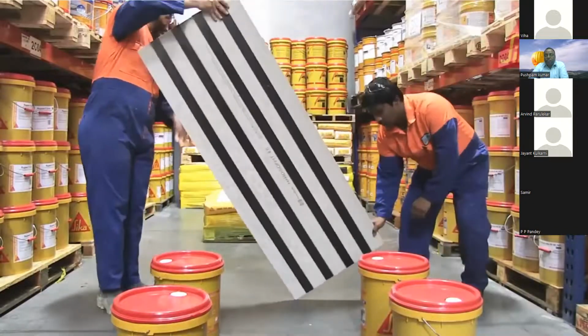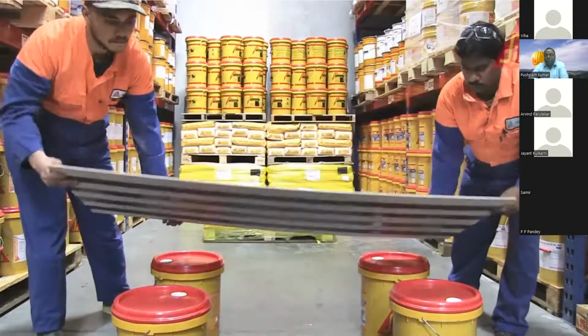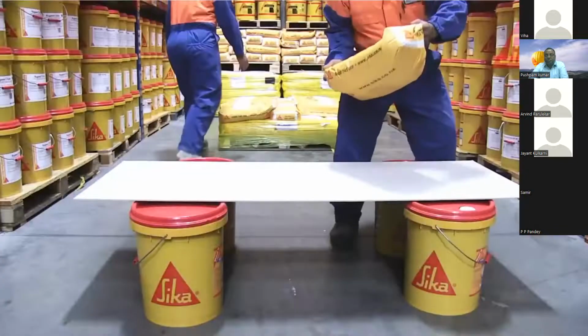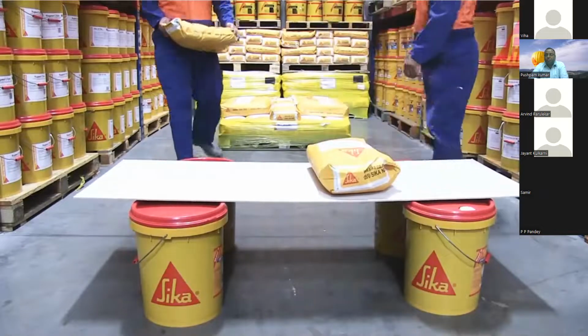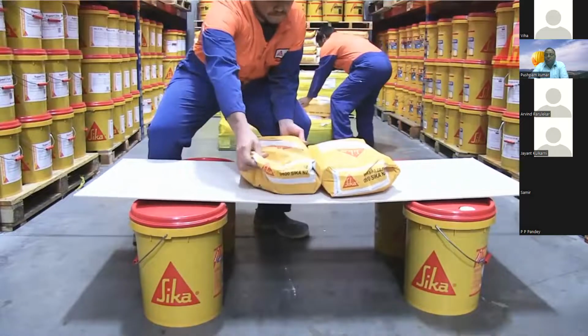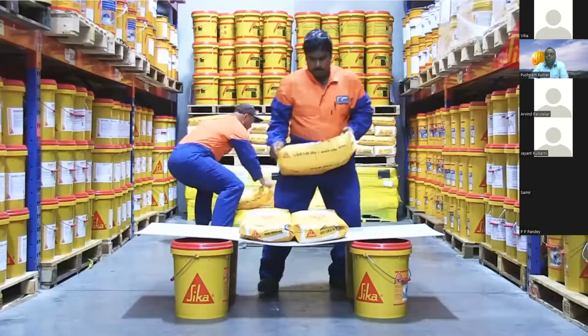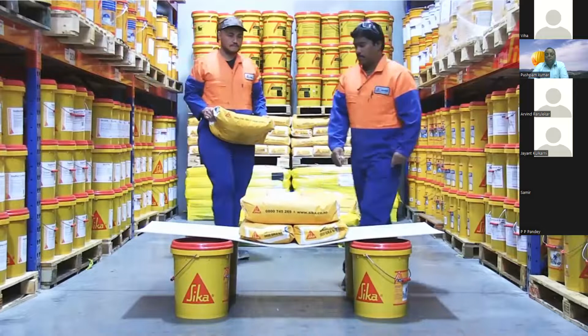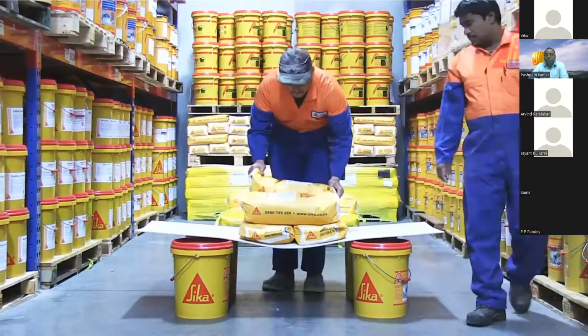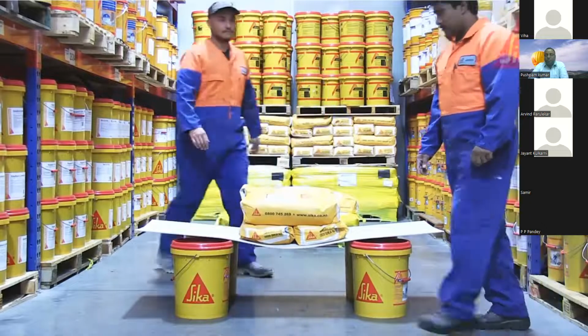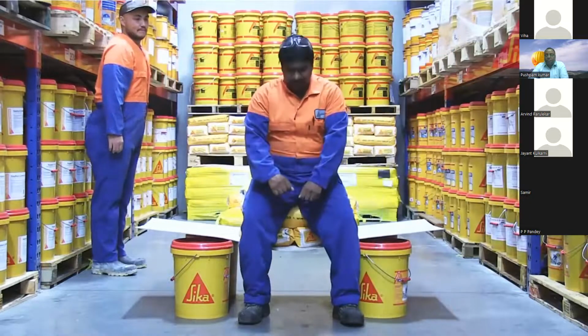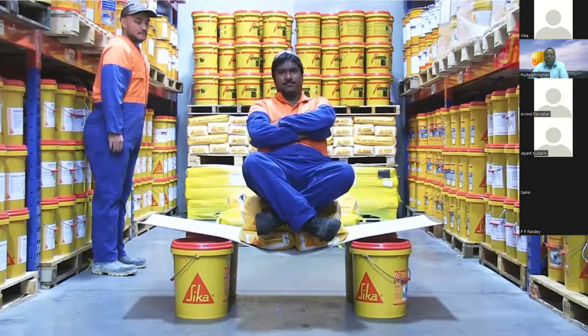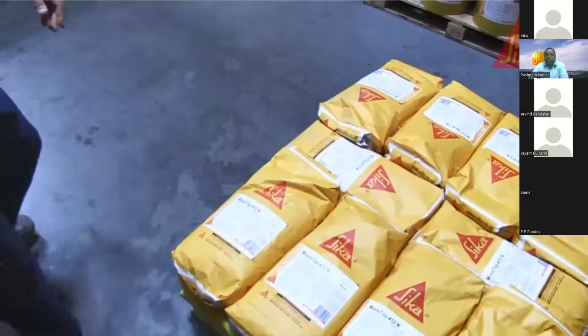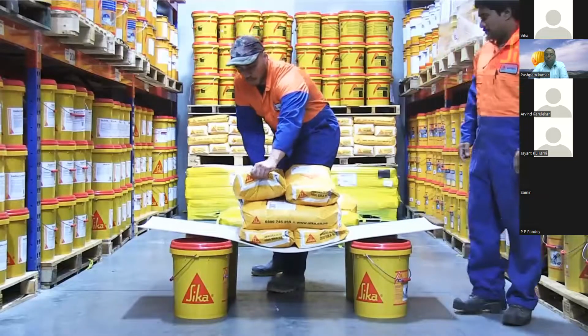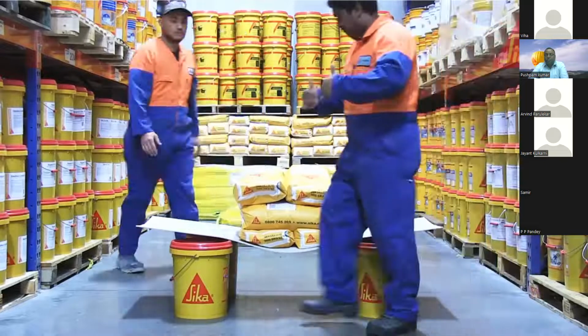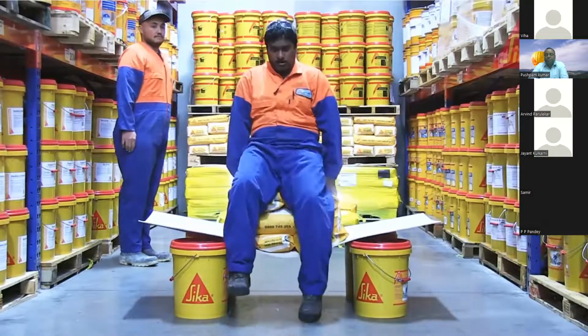But then we took the board that had been reinforced with the Sika Carbadur strips. On went 25 kgs. Then 50 kgs. Then 75 kgs. Then 100 kgs. Then on went 80 kgs of Navindra from the Sika warehouse. Not bad. Not bad at all. Then we added another 50 kgs, making a total of 150 kgs plus 80 kgs of Navindra again.